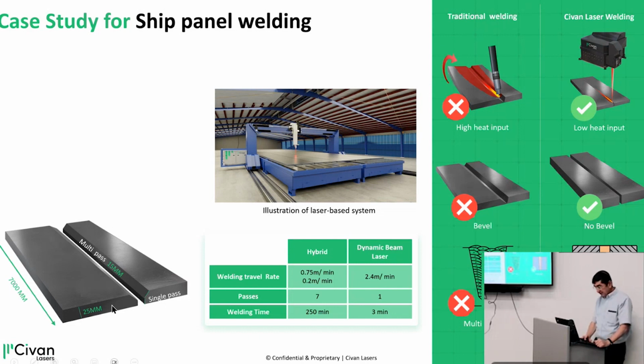For this 25 millimeter thick material, they do a root weld with hybrid laser. Hybrid laser is a laser with plasma. So they can do the first 10 or 12 millimeters, and then for the rest they had to go back and forth with a filler wire, altogether 7 times. It takes them today 250 minutes, and we're doing it in 3 minutes.